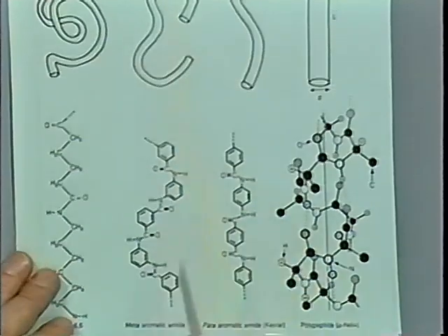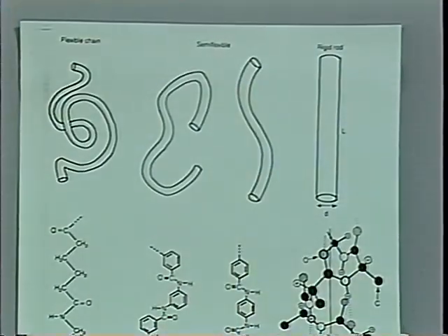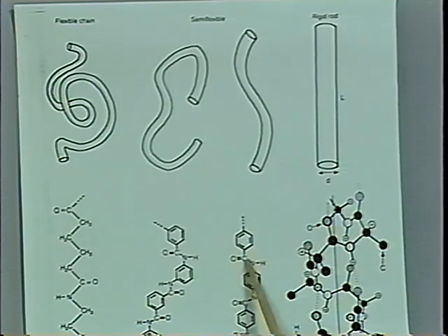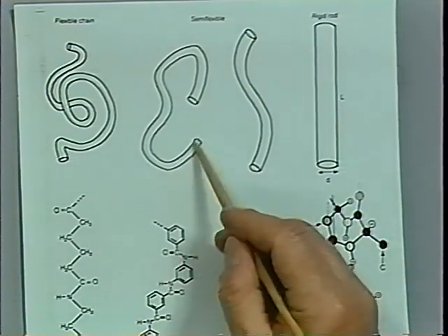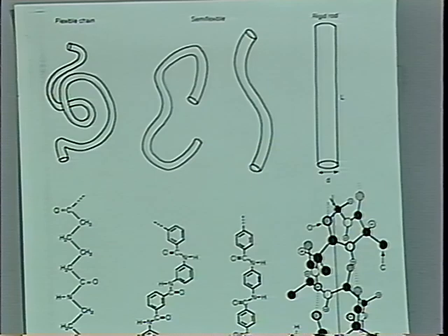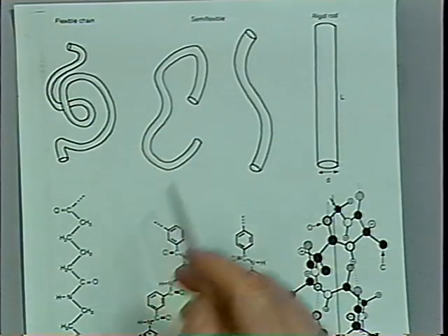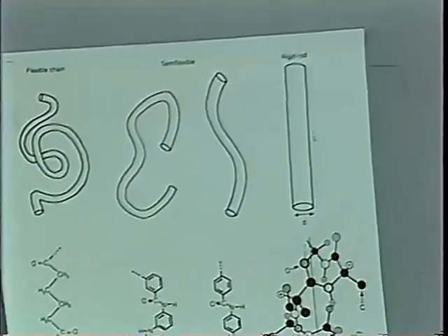Those molecules are semi-flexible. However, the semi-flexible molecules in groups, when they bundle up, increase their stiffness, and they are really acting as solid-like behavior. So the chemistry determines the molecular stiffness, and the flexibility can be described by the flexibility of those bonds. This would be Flory's rotational isomeric state model, or by some Kuhn lengths. We saw this in Muthukumar's lecture on molecular dynamics, or a persistence length, which is really the length you have to walk along the molecule until you have a new direction, which is disconnected from your original direction.